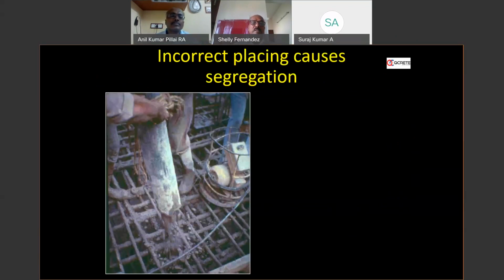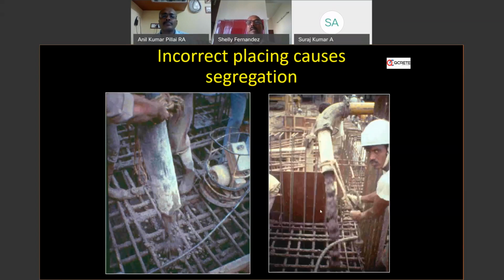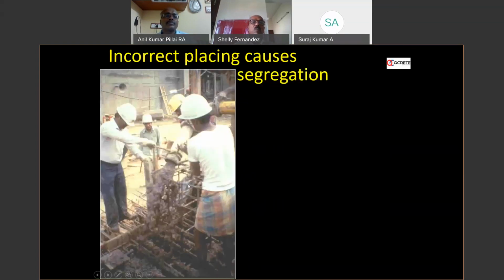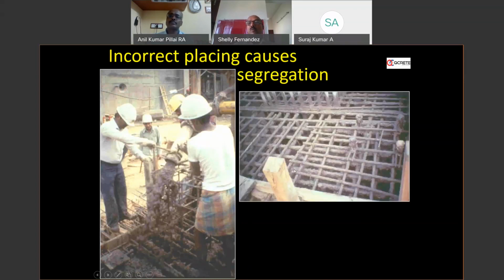Now, incorrect placing causes segregation. We can see the concrete falling onto the steel reinforcement and segregating. Even though you had made a very good concrete, if placing is not planned properly, whatever good concrete you made gets segregated, because you can see all the fines sticking on the steel reinforcement and only the coarser aggregates falling down. You can see here it is segregating more, falling on the steel reinforcement, and now falling more onto the pedestal. It is segregating further. At the end of the job, you can see it is mortar-coated steel reinforcement, actually. It is not epoxy coated. It is mortar-coated reinforcement, a bad job.